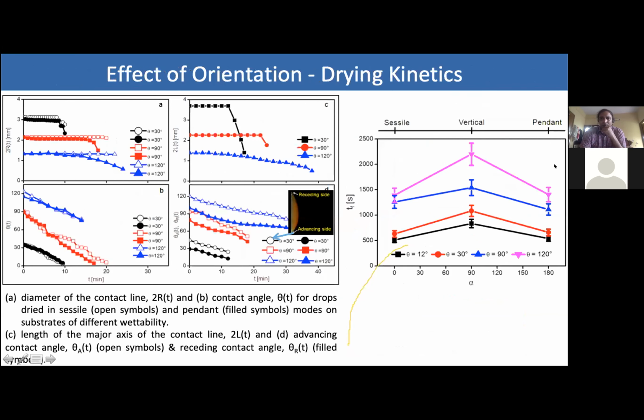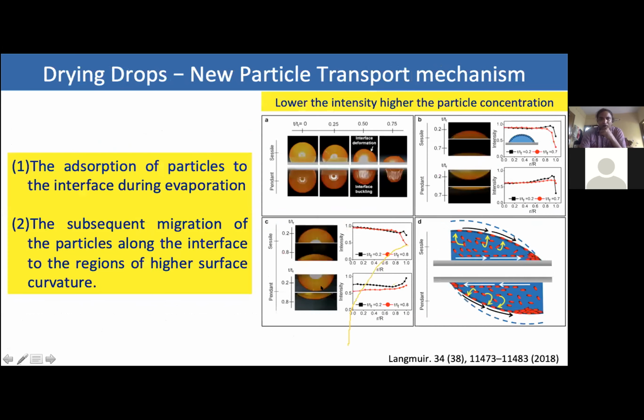So we have done a more detailed study of this phenomenon, and it turns out that the total evaporation time, that is the time that the fluid in the drop takes to completely evaporate, also depends on the orientation and also the wettability. If the substrates become less wetting, that means when the contact angle is, say, 120 in this particular case, you see that it takes a much longer time to evaporate. And if you look at the sessile and the pendant drop mode, the total evaporation time is lower. So this evaporation time also influences the nature of the deposit formed.